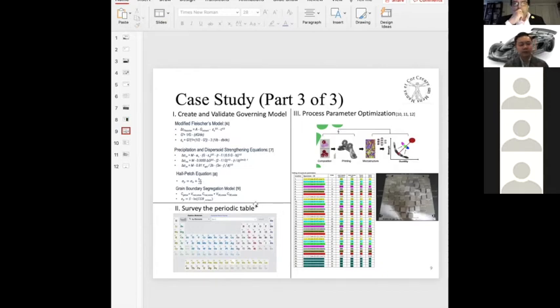With this model and our understanding, we survey the periodic table for solid elements, and then we optimize our process parameters to first see if the material is printable. If so, we go through a design of experiments to make sure that the parameters are producing the right microstructure that gives us our properties, and also our production rate. Going back to the governing model piece, the fundamental strengthening models are used.